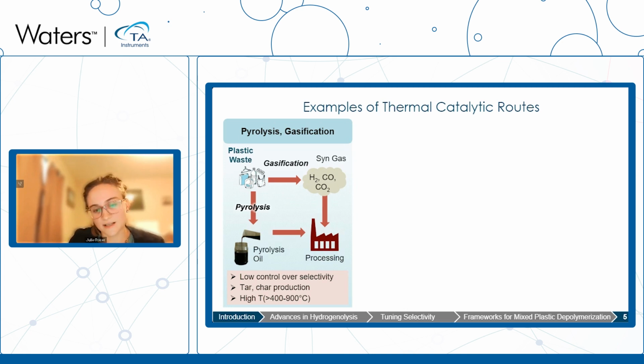And the state of the art that we might think about are pyrolysis and gasification. In gasification, plastic waste is heated up and converted into a syngas, which can then be processed downstream. In the pyrolysis process, the plastic waste is heated up in an inert environment to generate a pyrolysis oil, which can then be later refined.